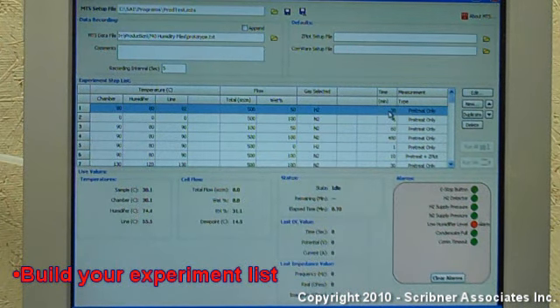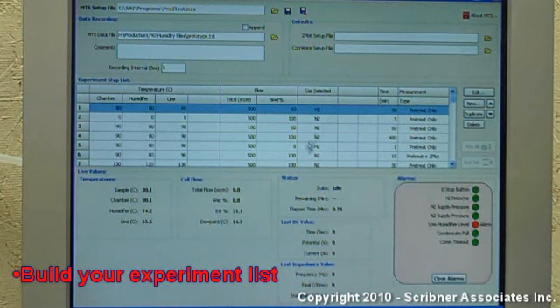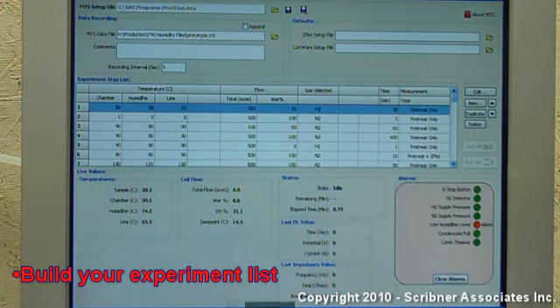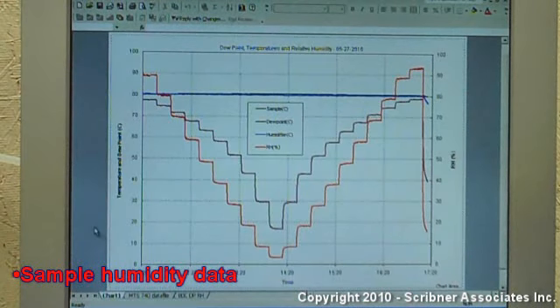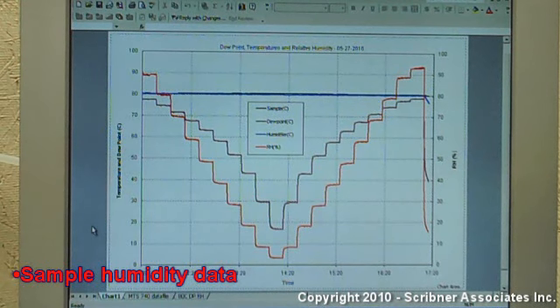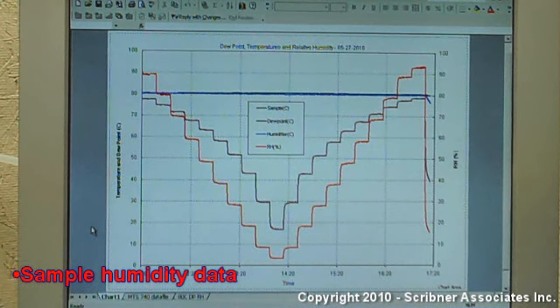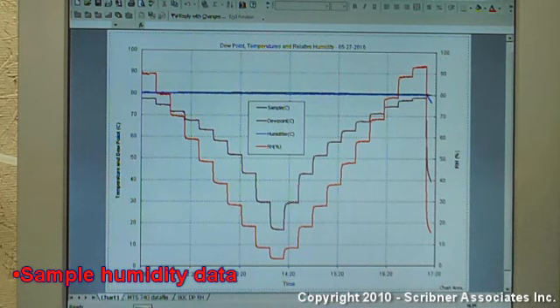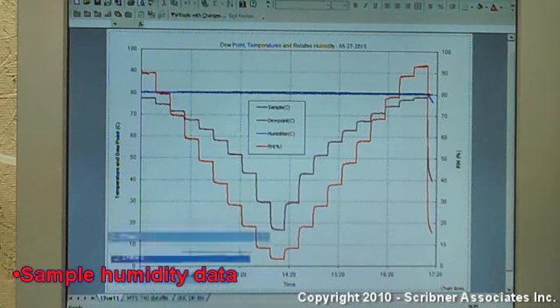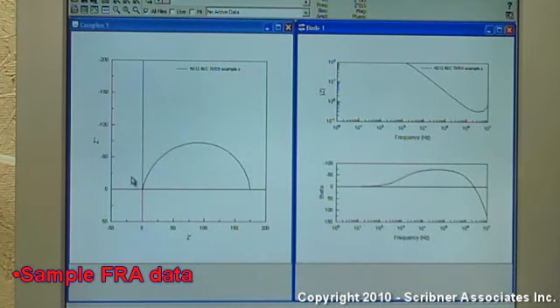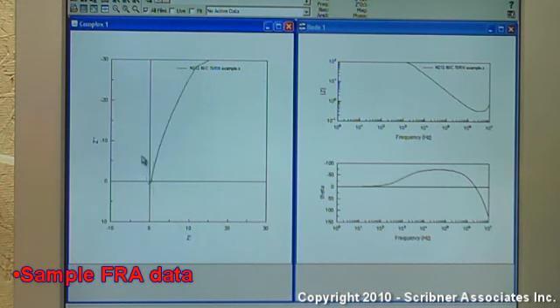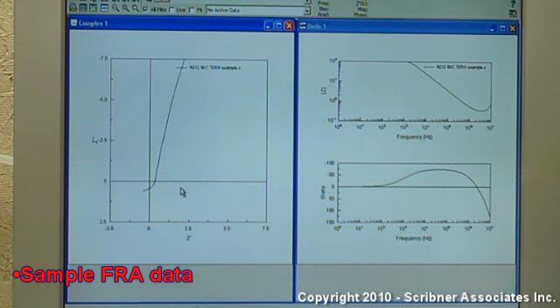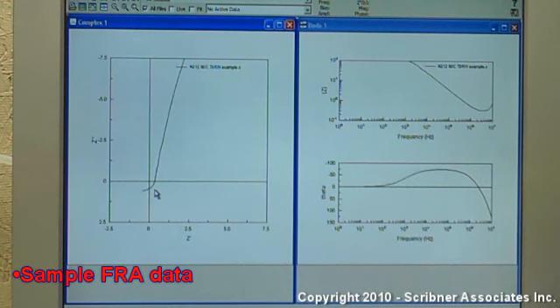Here is an example of a typical humidity cycle performed over a 6-hour period, displaying the step down and step up in relative humidity. The representative impedance spectra were obtained with the MTS 740 and a Solartron 1260 frequency response analyzer. The high frequency intercept is indicative of the membrane sample's through thickness resistance and is determined by fitting an equivalent circuit model to the impedance data in our ZView software.